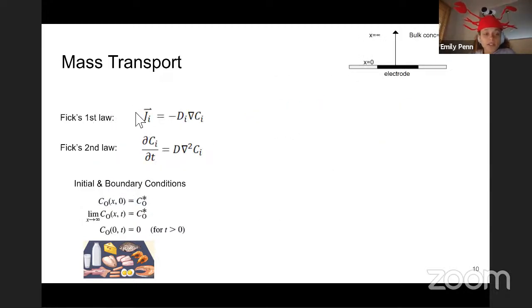So from the Nernst-Planck equation, once we get rid of the migration and convection terms, we're basically left with Fick's first law, which describes the flux related to the concentration gradient. This equation doesn't account for time at all. It's like a steady state equation. But then if we consider Fick's second law, which we get to by using Fick's first law and considering conservation of mass, then we can consider how the concentration changes with time as a function of the concentration.